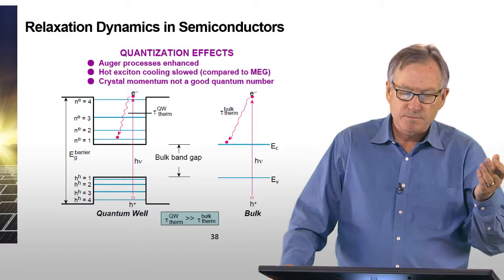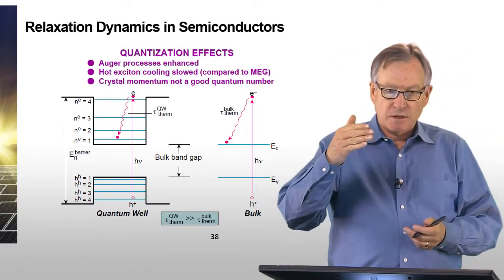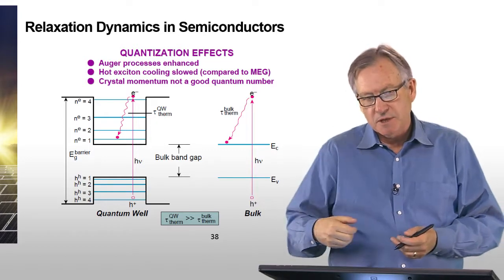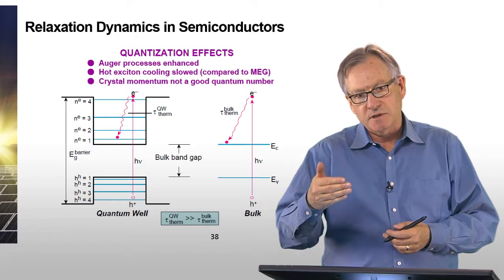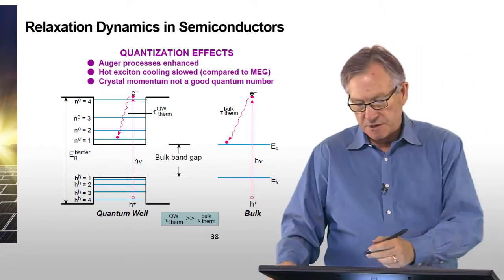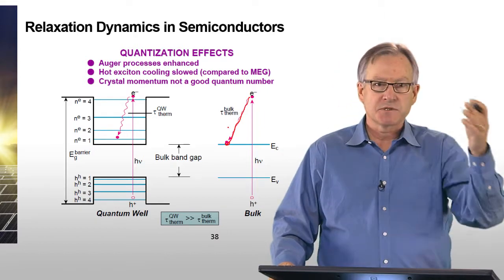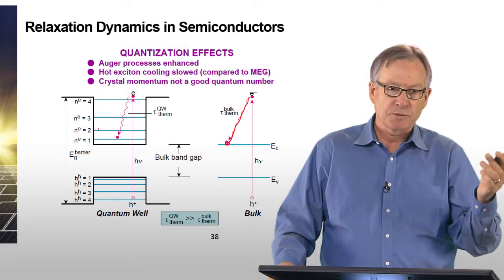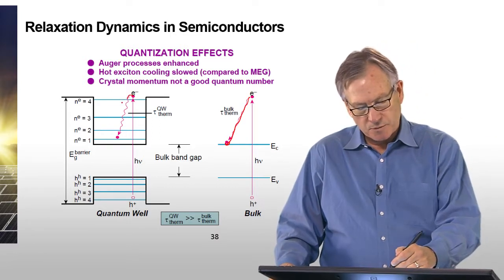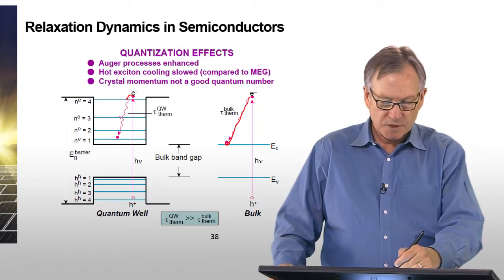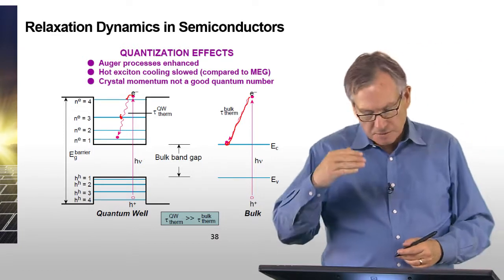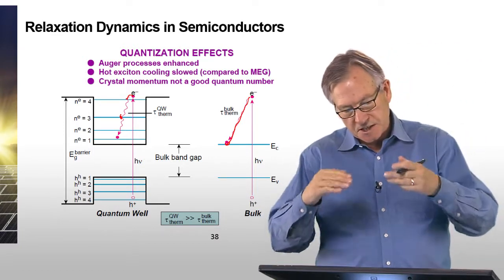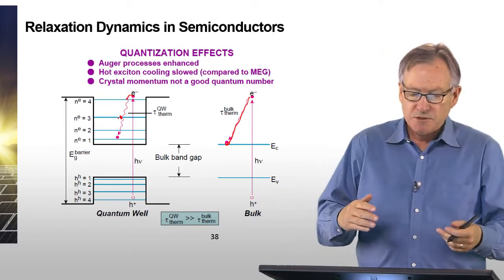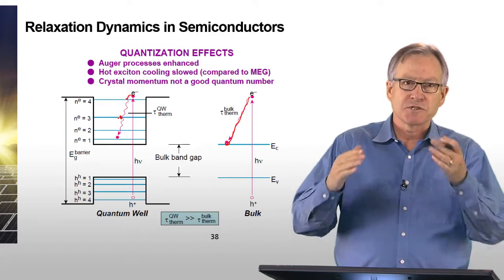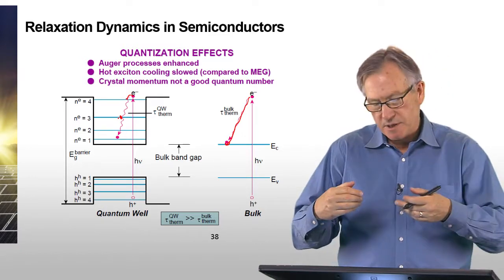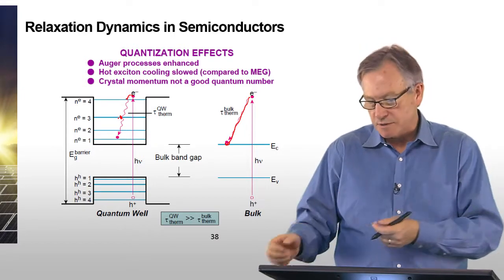And now when we talk about quantum confined systems like quantum wells, nanowires, and quantum dots, this relaxation dynamics can be slowed down. It can be slowed down because while in a bulk system you have a continuum of states that are available to scatter to, if you have a completely quantized system like a quantum dot, where you only have discrete levels, then it's impossible for an electron to basically emit a phonon and go from this level to this level and conserve energy. So this is a simple way of explaining why, because of density of states effects, thermalization can be slowed down. So we have a much better chance in nanostructured or quantum confined systems of slowing down energy relaxation and getting the higher temperatures that you would need in order to realize this hot carrier solar cell concept.